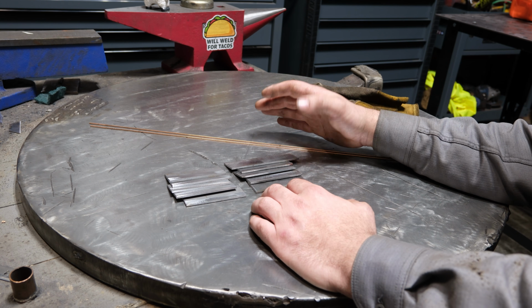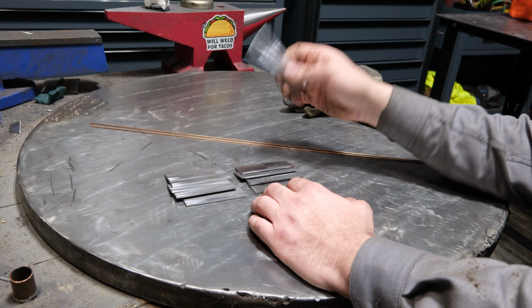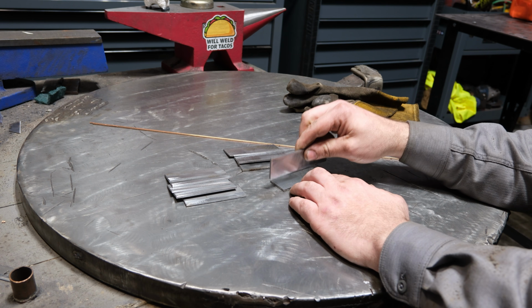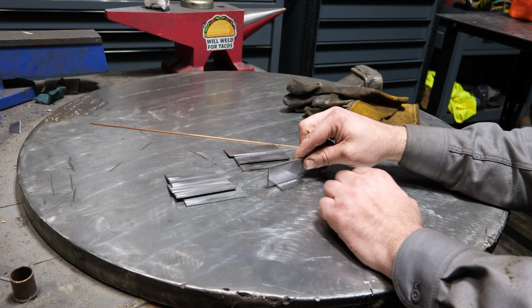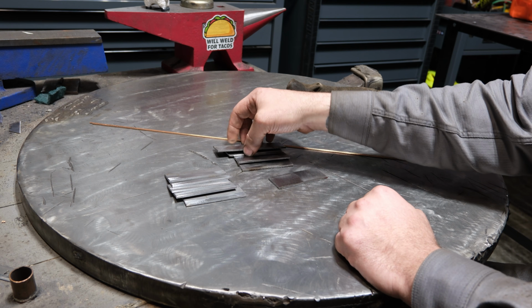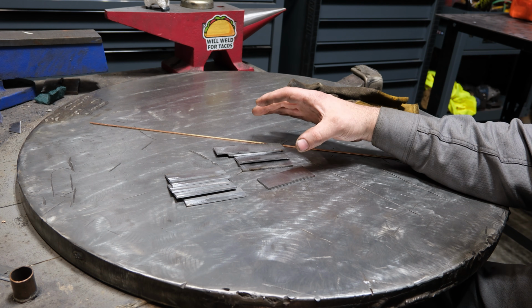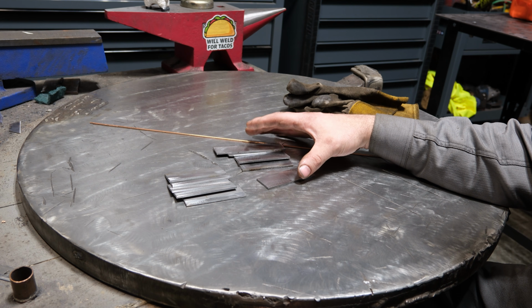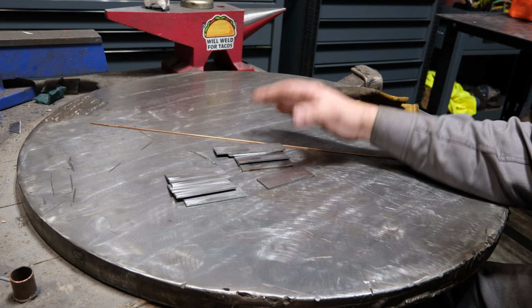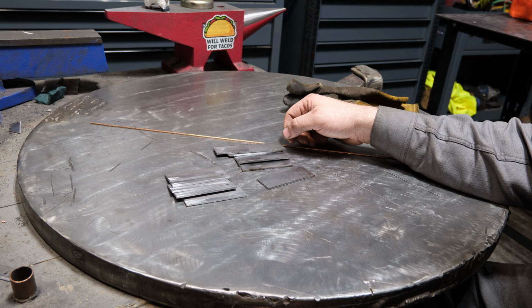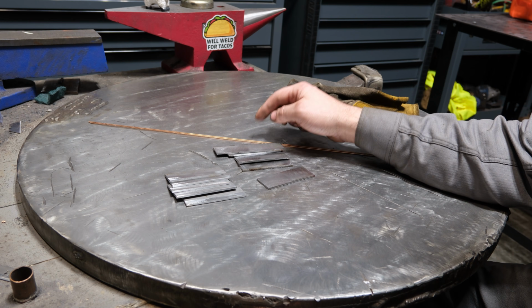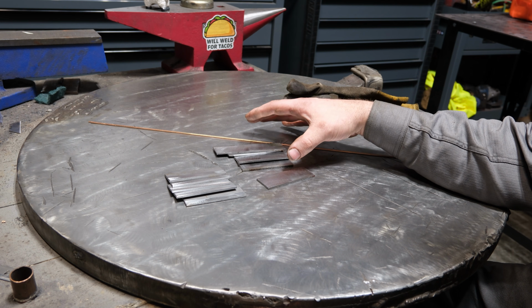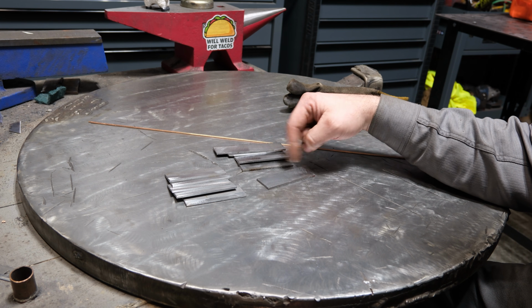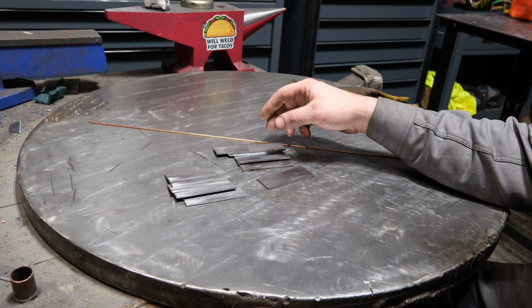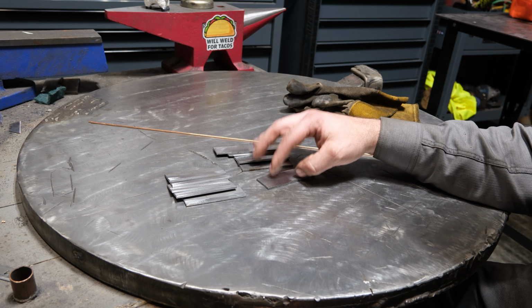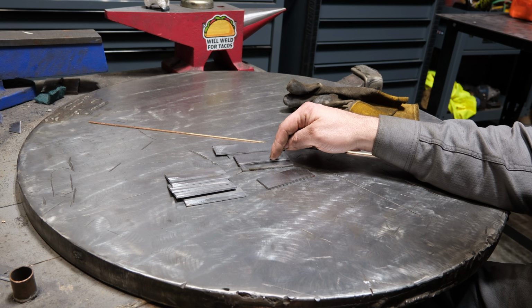Anyways, let's get into the topic at hand, which is fillet welds, which for those who don't know, some people call it a T-joint, but basically you have an upright plate and a bottom plate, and we're welding this in the flat position. And very simple to do this. However, if you haven't mastered the basics with TIG, aka arc gap control, your travel speed control, your tungsten angle, your filler rod addition, all of those things you really need to have a good handle on before you go and start doing this, because you're just going to end up scrapping a lot of metal that would otherwise be decent. So for the setup that I'm going to be using, I'm going to be using 1/8 inch material.